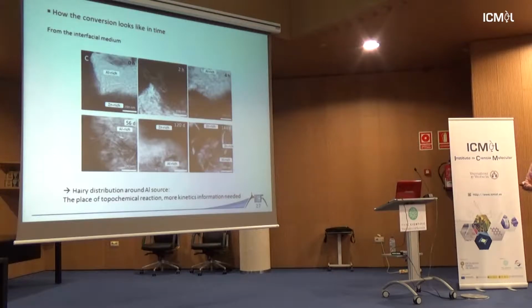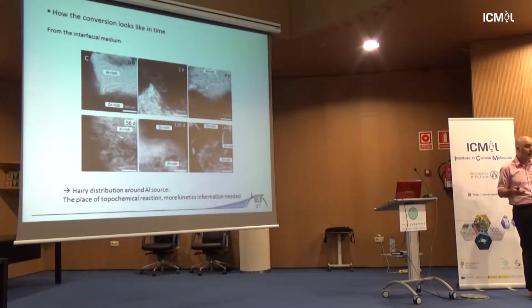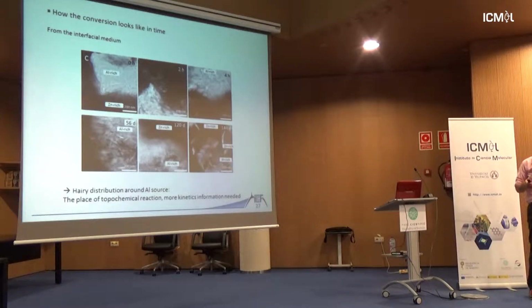And what's more interesting here is at the interface, where you can see that at first there is no interface, and you start to see some evolution at the interface. And little by little, you start to form the platelets just in the vicinity of the grain of a little aluminum-rich domain.